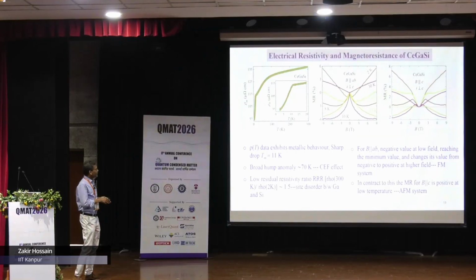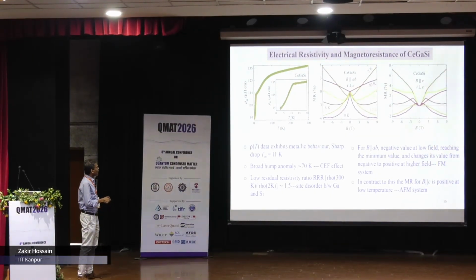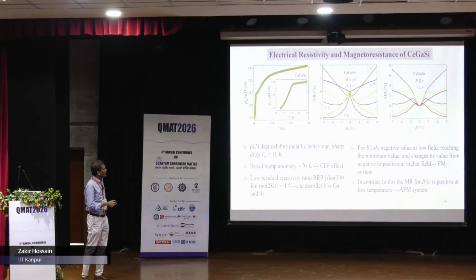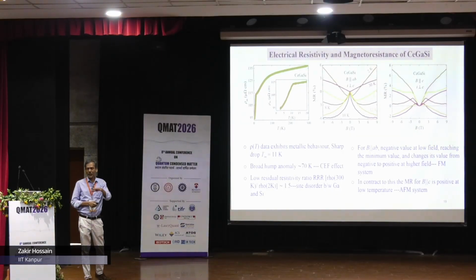Okay. So the resistivity is decreasing with decreasing temperature as expected for a metal, and this is the reduction of spin disorder scattering at the magnetic order. And also the magnetoresistance we measured both for B parallel AB and B parallel C. The current is perpendicular to C, meaning a thin crystal, so we can flow current only in the AB plane. Yeah? And so what do they say? So this is 10 Kelvin, okay, 8 Kelvin, and this is 2 Kelvin.